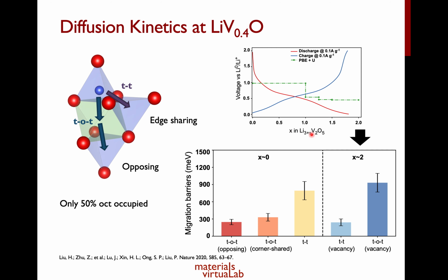What about at the end of the process, which is closer to Li5V2O5, x equals 2? Now again, we still have our tetrahedral and octahedral sites. The difference is that at Li5V2O5, only 50% of our octahedrals are occupied. Remember, at Li4 we have a sudden redistribution of lithium. Basically, we now have only 50% occupied octahedrals, while we still have a lot of occupied tetrahedrals and a lot of unoccupied tetrahedrals.